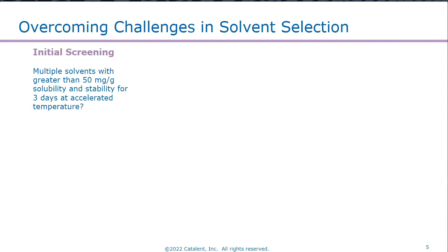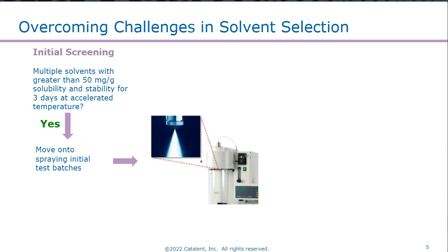So the initial screening, we'll look at multiple solvents, and we're aiming to find solvents that give solubility of the API at around 50 mg per gram of API in solution. So that's around a 5% drug load in the solution. And ideally, we want to have the API stable in solution for a few days to enable long spray drying times at the latter end of development. So if we can achieve that, then we can proceed to spray drying the initial test batches.